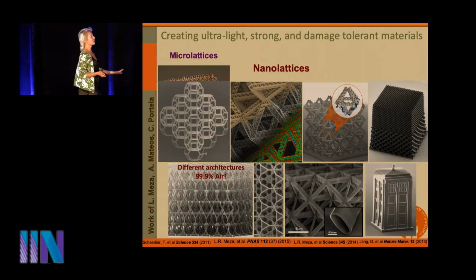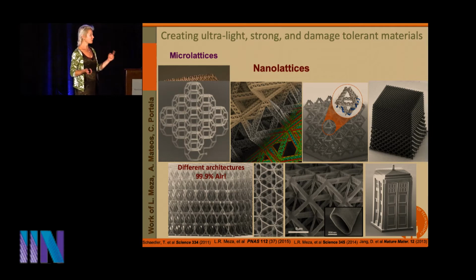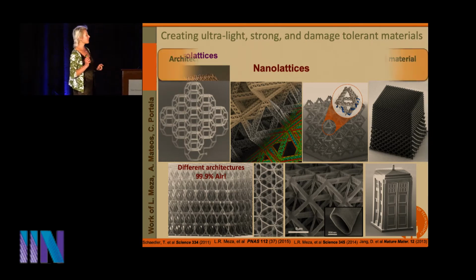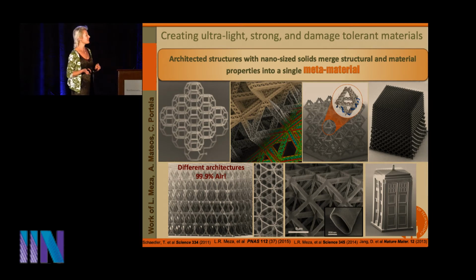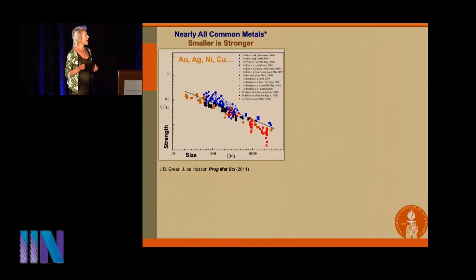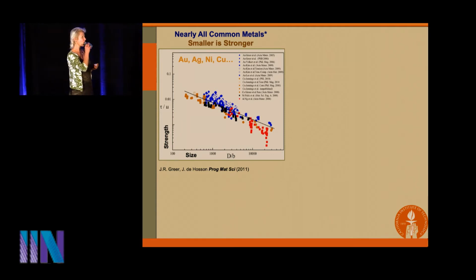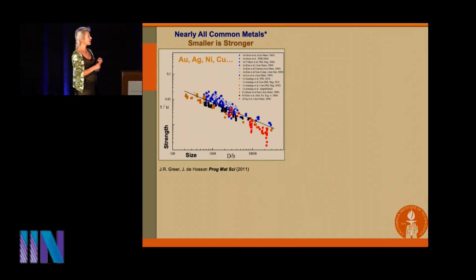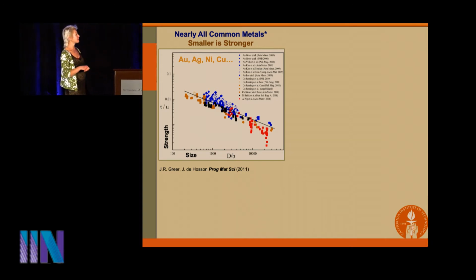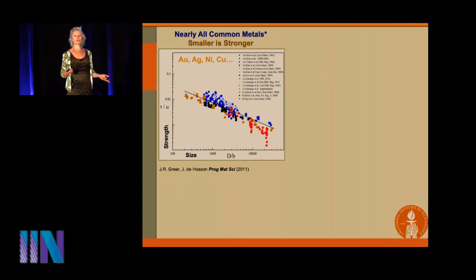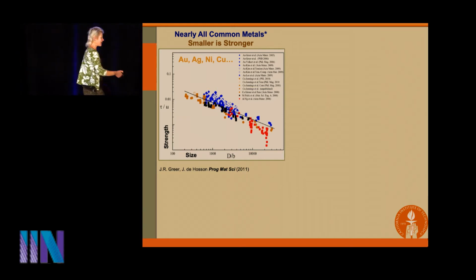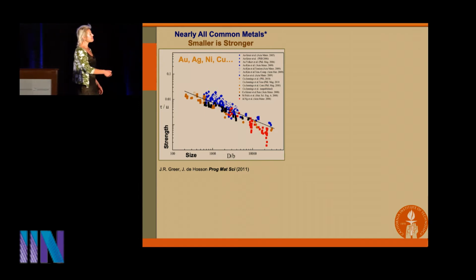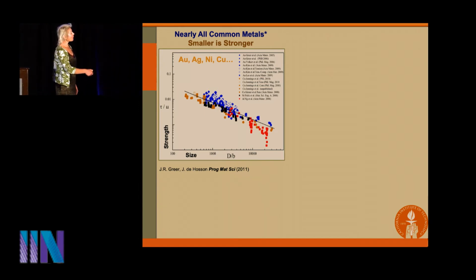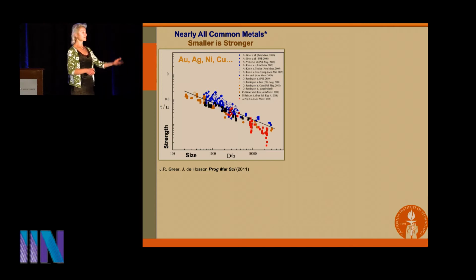So this is what gives them the lightweight, but what we're after is the combination of the lightweight and strength, and this is where the nano size effect comes in, very important. At the nanoscale, all the common materials exhibit a so-called size effect, which turns out to be very pronounced and very useful. If you look at a variety of common metals, what I'm showing you here are metals like gold and silver and copper and nickel in their single crystalline form, so no grain boundaries. And what you're seeing is that the strength becomes tremendously higher. There's a tremendous amount of strengthening in a power law fashion as you reduce the dimensions.